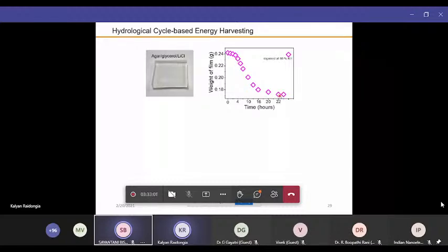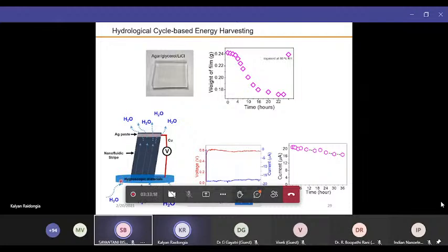Now, when you put it back in the atmosphere, within 4 or 5 minutes it regains all the water molecules it lost, at 80% humidity. It dehydrated in 22 hours. Now, when we connect our device to these hygroscopic materials, which collect water from the atmosphere, at the other end of the device this water will be constantly evaporating through the nanochannels. Then we can just put this device in the atmosphere, without anything else, and get energy for a very long time.